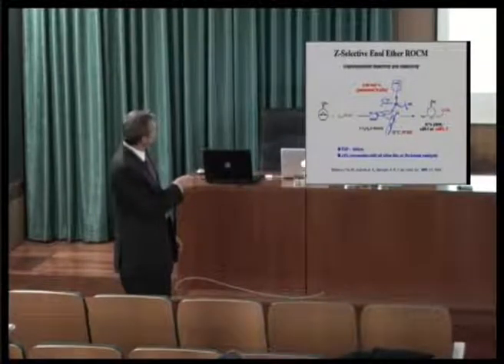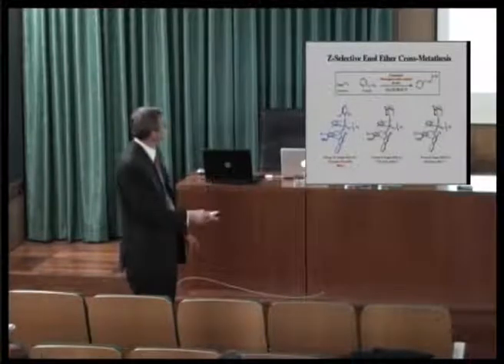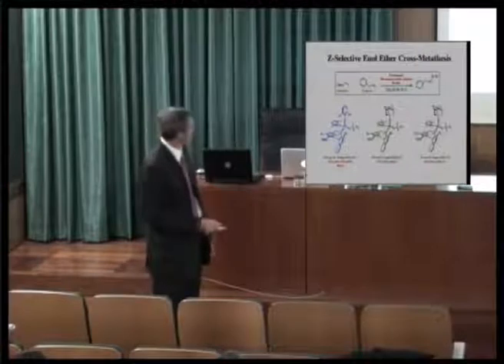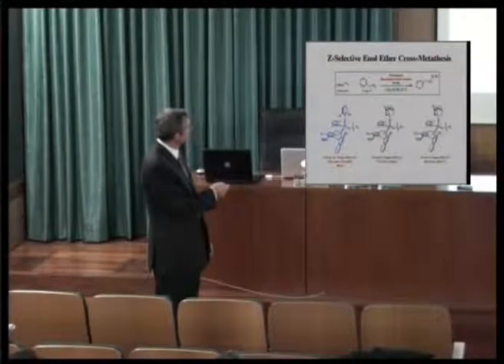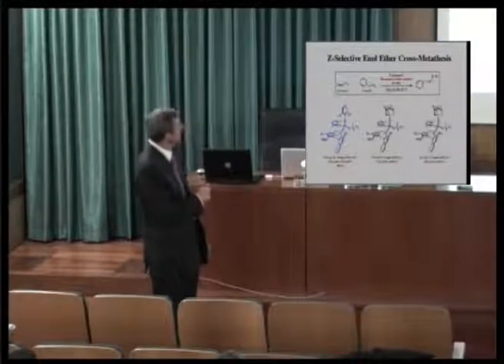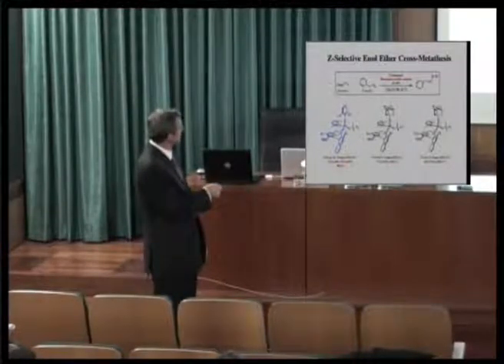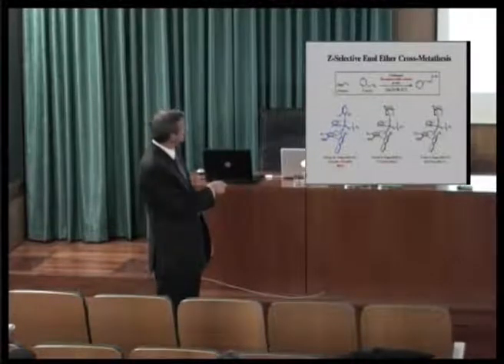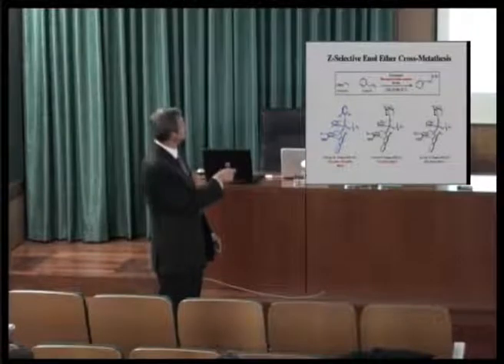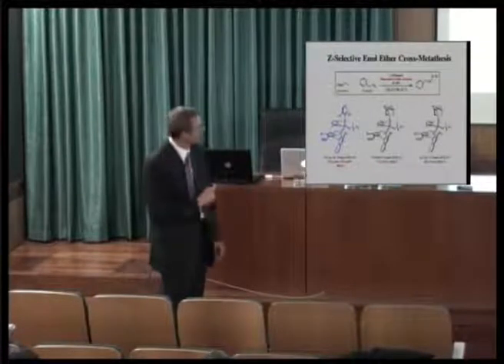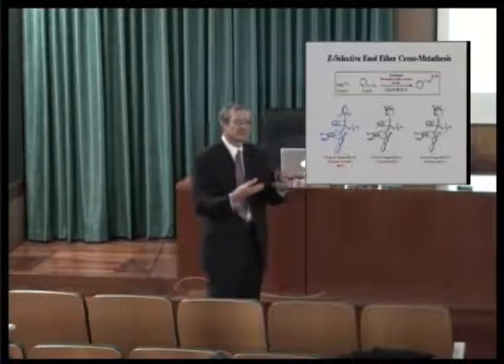So this is a ring opening cross. It's enantioselective, but what is really important is just the cross reactions, selectively Z. So that would be, let's say, this allylbenzene plus the vinyl ether to give this Z enol ether product. And we can do that with variations of the catalysts I've talked about, greater than 98% Z, very Z-selective, and pretty good yields, 82% conversion, 76% yield of the cross product selectively, none of the homo products, or at least no more than 25%. So that's one of the most difficult reactions you can imagine.